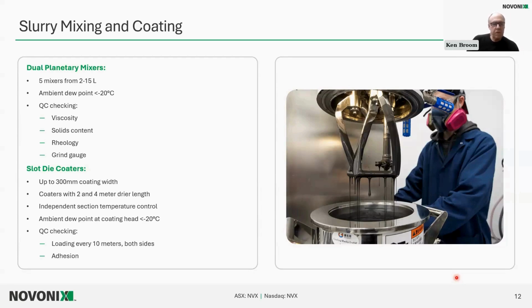We have a couple of slot die coaters that can coat up to 300 millimeters wide on 330 millimeter wide foil. One of the coaters has a 2-meter long drying section, the other one has a 4-meter. Each of those drying sections is made up of 1-meter individual sections, which have independent temperature control. The ambient dew point in the coating head area is less than -20 degrees C.